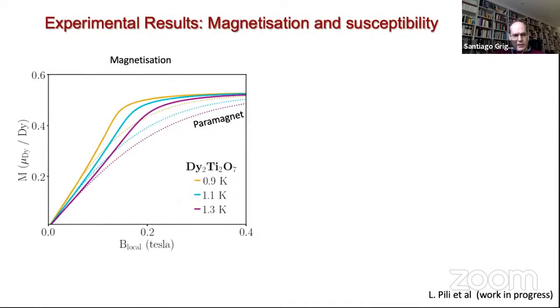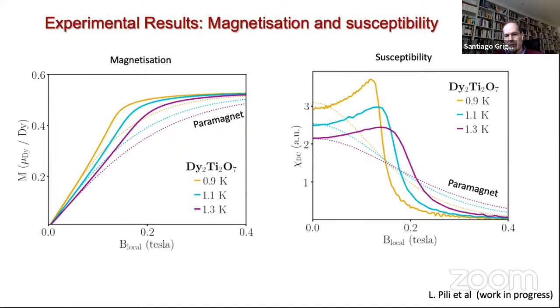Okay, so these are some experimental results. This is the magnetization for dysprosium titanate as a function of field. These are the solid lines. They're compared with what you get from a paramagnet, and you can already see that the rise towards saturation is sharper for dysprosium titanate than for a paramagnet. But when you look at the susceptibility, simply the derivative with respect to field of these curves, you find that while it's true that at low temperatures and high fields, the system does look like a paramagnet, I mean, follows the scaling of a paramagnet, the behavior as a function of magnetic field is quite different, quite distinct. So here, instead of just a monotonically decreasing susceptibility, you get this sort of